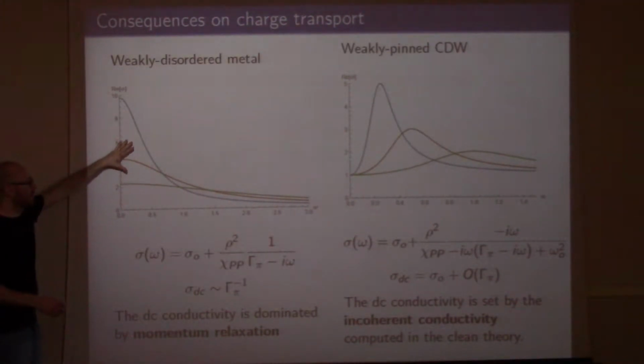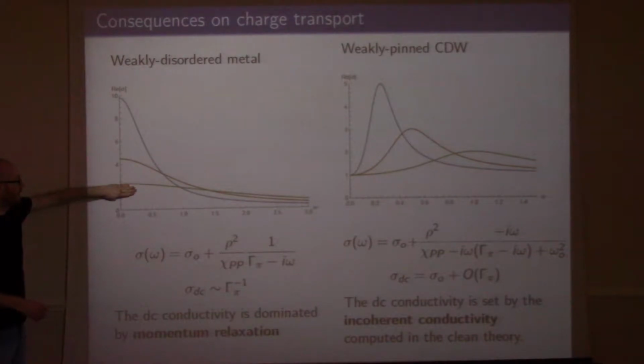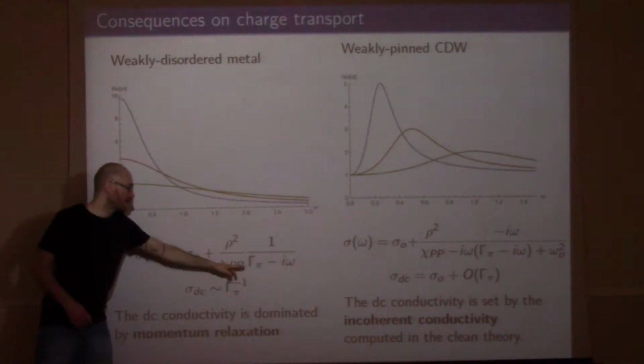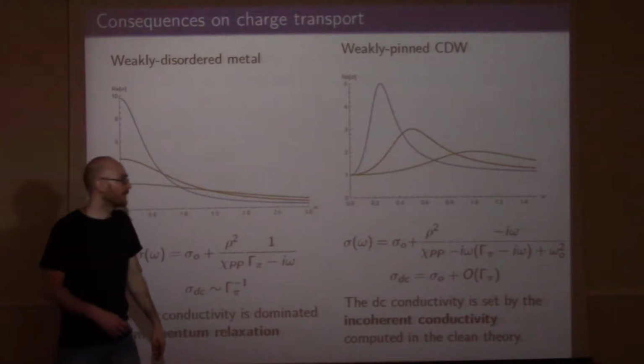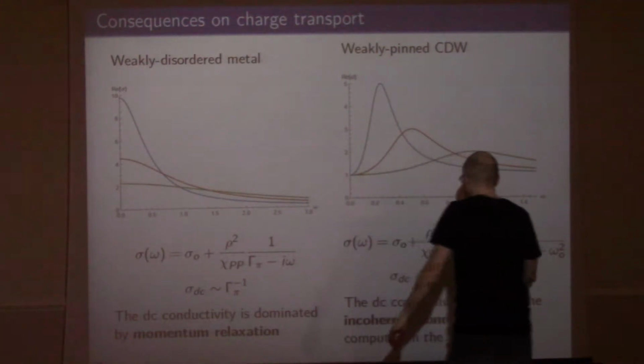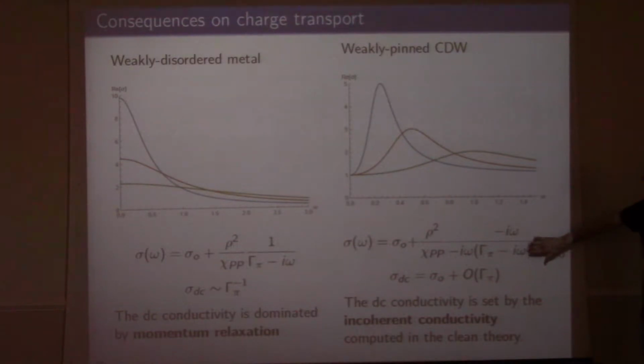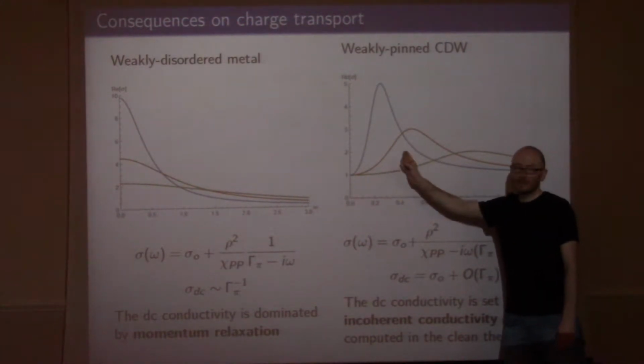So this is what this picture shows. And then the blue curve, orange curve, and green curve are what you get when you increase the value of this guy. Now, on the other side, this is the formula that you get for the optical conductivity of a charge density wave. You see that it looks a little bit different, because essentially now you have this pinning parameter, omega naught, that appears in the denominator. And this has shifted the location of the pole. Instead of having a purely imaginary pole, now the pole has a real part because of this guy. And because the pole has a real part, it shows up as a peak at finite frequency, not at zero frequency.